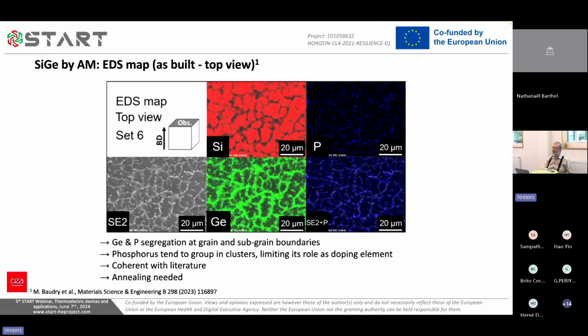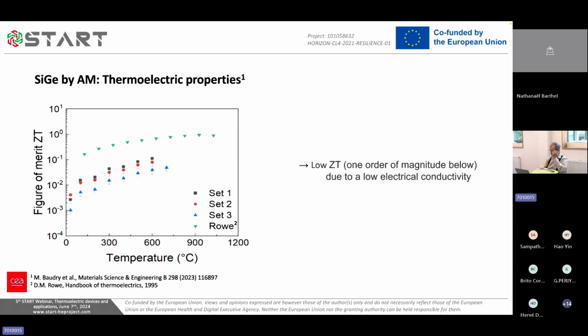And if we look at the EDS map, you see that there is material segregation. Silicon and germanium tend to separate, and even the dopant, phosphorus here, is clustering. So this is not favorable to thermoelectric materials, of course, and this means that some annealing is needed, and this is a work in progress. And of course, the result of this is poor thermoelectric properties.